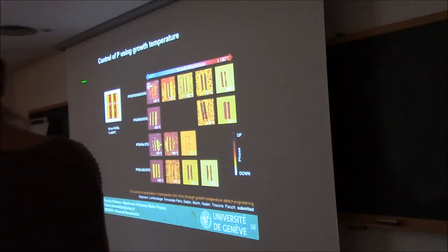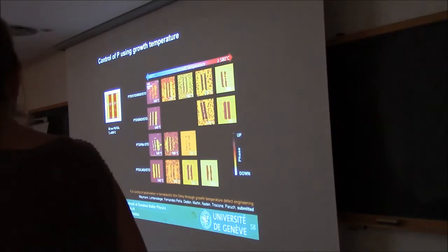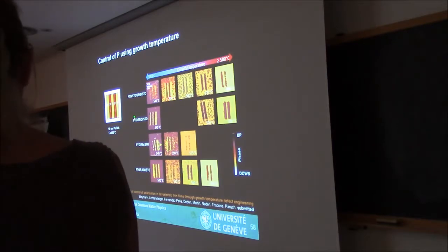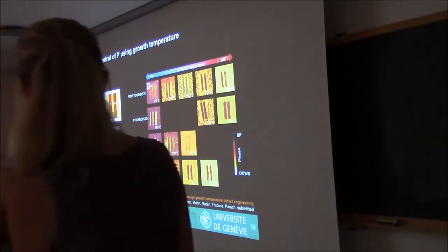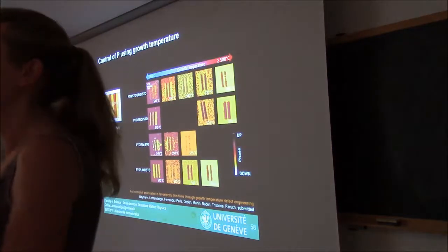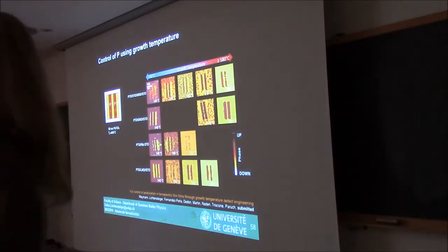And this is true not just for this particular set of electrodes, but here you have other series. So this is PTO on strontium ruthenate without the STO spacer layer. This is PTO on Nb-doped STO, and even PTO on LNO electrodes. Always the same thing. You can always find a temperature where you have monodomain up and a temperature where you have monodomain down, and a set of temperatures where it's polydomain.